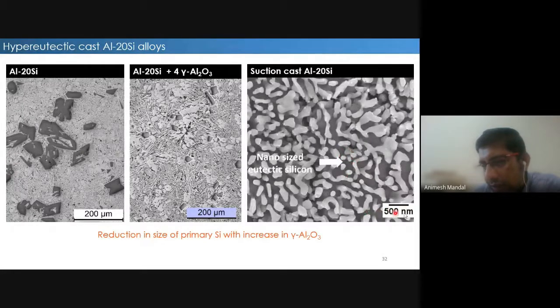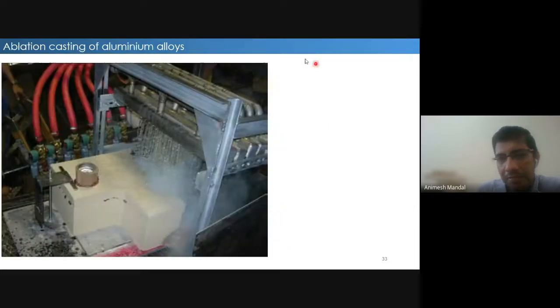So this is a 500 nanometer bar, right? So this is quite a bit less than 100 nanometers. So it's possible to generate nano eutectic silicon using a fast cooling rate process, and the properties which we have achieved for this are exceptionally high. It's very high for a normal hypereutectic aluminum silicon alloy.